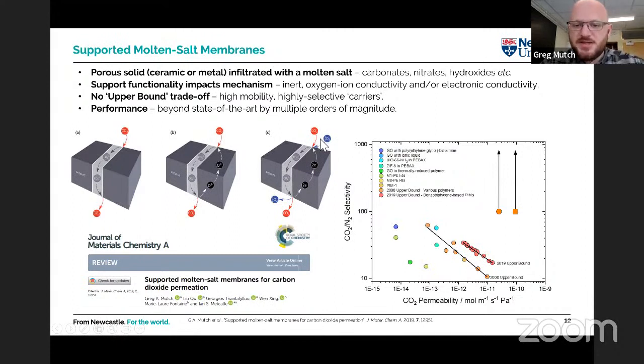And in that case, you can co-permeate carbon dioxide and oxygen in a fixed ratio. So to make that carbonate ion, we need a half oxygen for every CO2. So we can permeate CO2 and oxygen in a 2-to-1 ratio. So that's quite interesting for controlling the ratio of two gases that pass over a membrane. If you're interested, there's this review paper that was published in 2019. This talks about all the different properties, all the different applications of supported molten salt membranes.